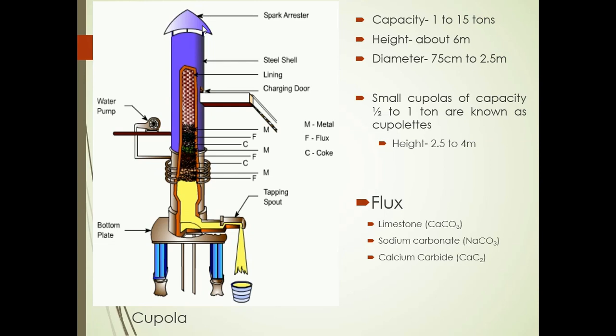Coke: in this cupola furnace we are using good grade anthracite coke, which has a low sulfur content, because if coke has more sulfur content, that sulfur is going to be absorbed by the molten metal, and unnecessarily the sulfur percentage of the metal increases, which will change its mechanical properties. That's why we also have to select good grade low sulfur coke. Again that sulfur causes environmental pollution, because sulfur oxides may be formed, that is sulfur dioxide or sulfur trioxide. Sulfur trioxide is responsible for acid rain, and sulfur dioxide is responsible for various health diseases related to our respiratory system. Both gases are very harmful. That's why we have to select coke which has low sulfur.